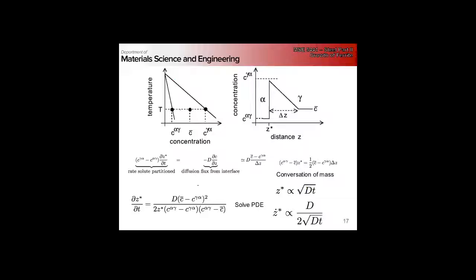It's definitely going to be skewed, right? Because only the very earliest ones are going to grow. There's a lot of catch-up time. Nuclei that appear later are growing at a faster rate, and the bigger ones, their rate keeps slowing down. So eventually there's a lot of time for catch-up. So if you think of idiomorphs in the center of the grain, you have a reasonable dispersion of inclusions for them to nucleate on - you're going to have them all be about the same size in cross section, as opposed to something that's nucleation limited where growth slows down. Then you're going to have a couple big ones.